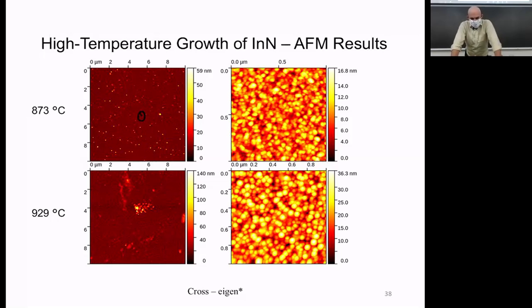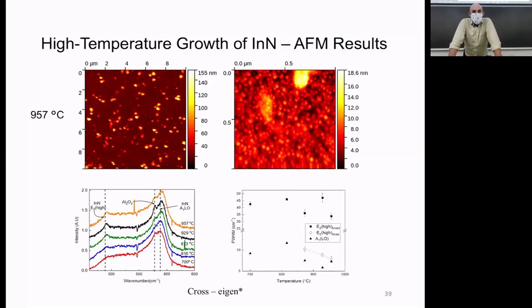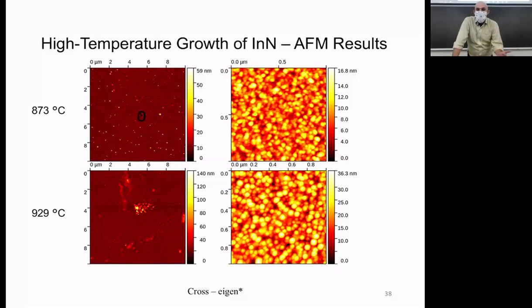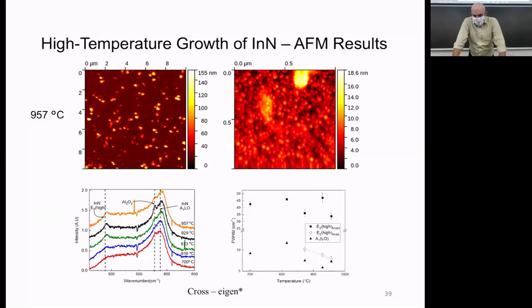And I get the same thing at 929. And when I look at 957, those big speckles are huge. There's not really a way to get a good scan without some of that speckle on it. I get, again, a similar background, but now it's tainted by all these speckle things. What we suspect is that those speckles, since they only appear in the 3 higher temperature samples, are related to this E2 high sharp. So we seem to be getting some material that is disordered, scattered across my surface, and we seem to be getting crystals that are growing on top of it. That's cool, but unfortunately, it's not what we were looking for.